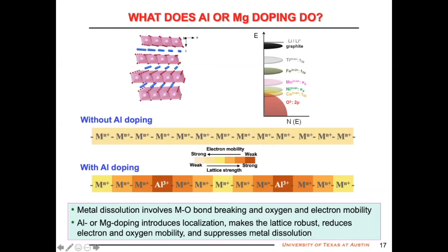So what is the magic with aluminum or magnesium or other dopants? Of course, there are small differences in the energy level among manganese, cobalt, and nickel, but they have edge-shared octahedra. So the metal ions are directly seeing each other. So there is a good flow of electrons, I would say a highly delocalized system. The electron mobility is good.